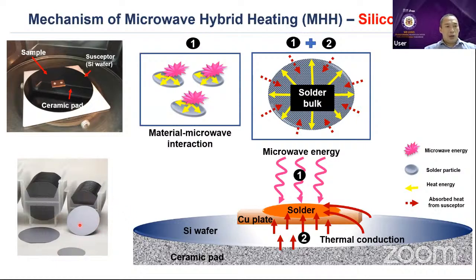So I just use this one and put it here, right? And these are my samples, the solders on the samples on the copper substrate, and this one is the susceptor. But because the temperature is very high, it can break the glass from the microwave here, right? Normally they provide the glass, so we just put the ceramic pad here. I'm sorry, this arrow should be referred to this white ceramic pad, right?